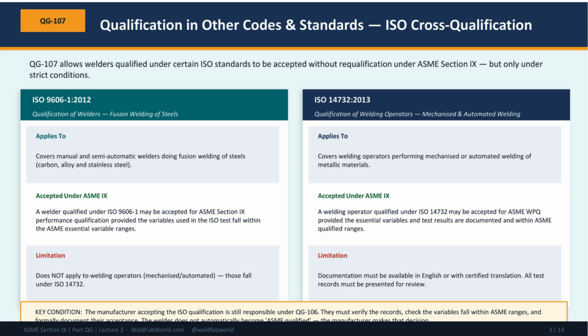What are those conditions? First, the welding of the test coupon must have been done under the full supervision and control of the qualifying organization. Supervision cannot be delegated. This is the same QG 106 responsibility principle we covered in Lecture 1. Second, the essential variables for the welding process must be recorded on the qualification record, and the ranges qualified must be listed. The code is clear that while the actual values on the record may look the same between an ISO and ASME record, the ranges qualified will be different, because Section IX computes them differently from ISO 9606-1. Third, the test coupon material must be drawn from base metals assigned a P-number under QW-420, and filler metals must be assigned F-numbers per table QW-432. This ensures full interchangeability with ASME materials classifications.